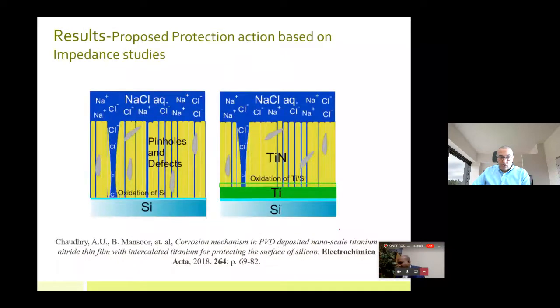The overall process that we were able to uncover was that the pinholes and defects that exist when you deposit these materials, they're really the controlling factor. If you're able to deposit a solid layer of metal on top of whatever substrate you have, you can have a better response. But this begs the question: if the substrate is not a nobler material, you'll run into galvanic corrosion issues. So that's where we were.